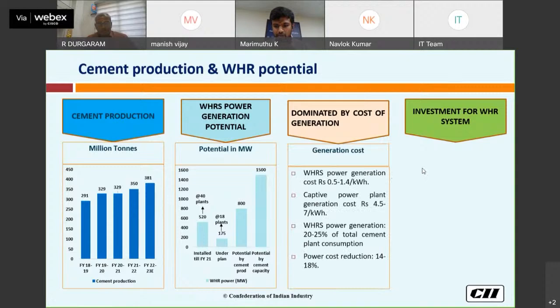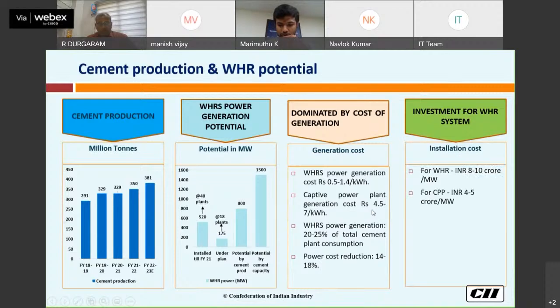The reason we have to go for WHRB is the operating cost. For a captive power plant now, due to the coal crisis, the power cost is more than 6 rupees. Generally we get between 4.5 and 7. But in WHRS, the operating cost will be 0.5 to 1.4. So with WHRS, 20 to 25% of the total cement plant consumption we can manage, and it also reduces the power cost by 14 to 18%. So out of 100%, 20 to 25% we can cover with this WHRS generation.